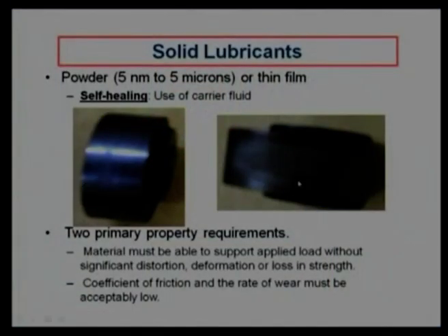Now, there are two important requirements for a solid lubricant. It should be able to support the applied load, and it should not tear away. The structure of the solid lubricant should not get distorted. We did a number of experiments and found that graphite gets distorted in its structure. Sometimes it is effective, sometimes it is not effective under high load conditions. There should not be any significant distortion, which is why deformation or loss in strength is mentioned here.